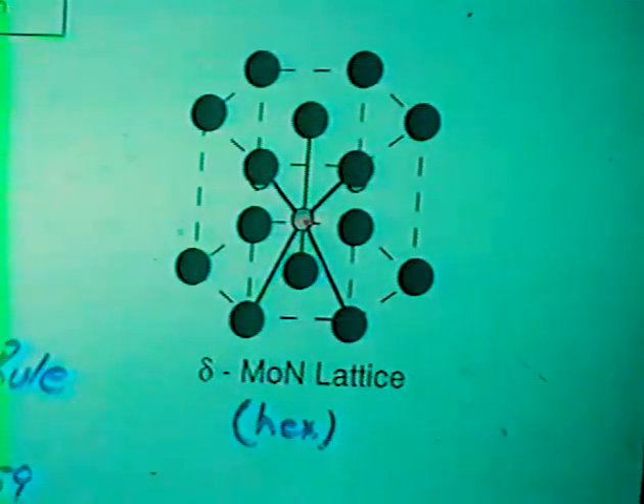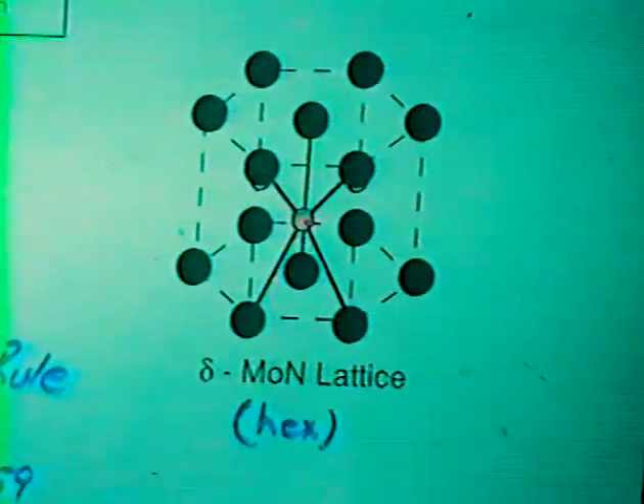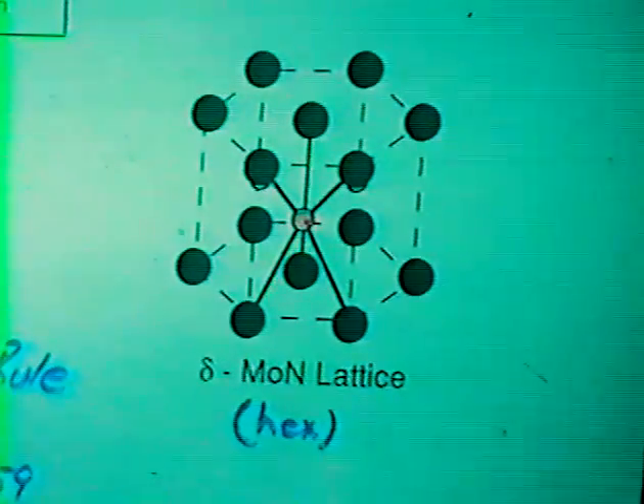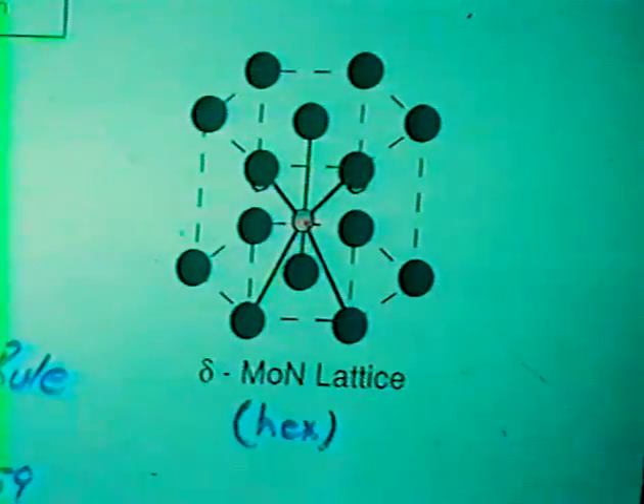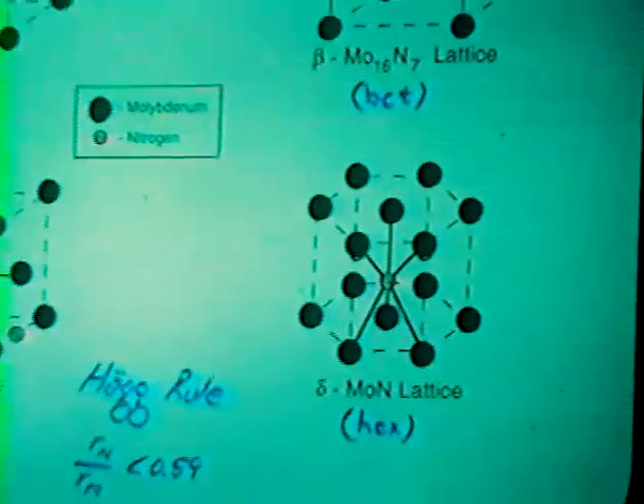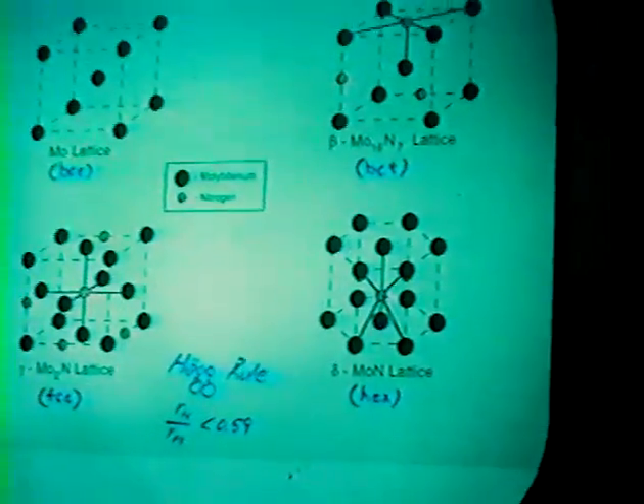The important issue here is that these are interstitial compounds. They can dissolve varying amounts of nitrogen. The lattice structure is not necessarily dictated by the nitrogen to moly ratio, although there are some limits if we look in the phase diagram for these structures. So it's not only important for us to determine what the lattice is, but it's important from a catalysis standpoint to also know what the nitrogen to moly ratio is.